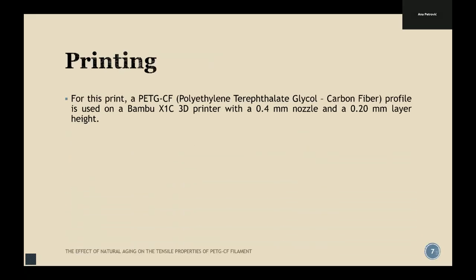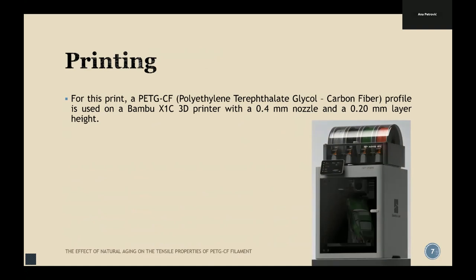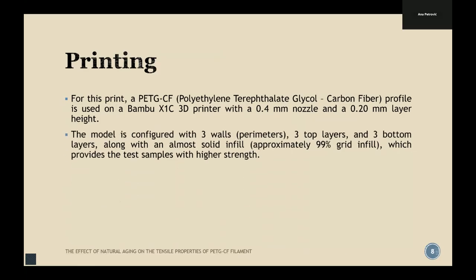For this print, PETG filament with carbon fiber reinforcement profile is used on the Bambu printer with a 0.4 millimeter nozzle and 0.2 millimeter layer height. This is the look of the printer, a standard printer with an enclosed chamber for thermal stability during the print.